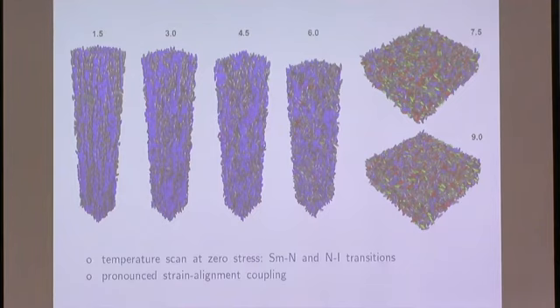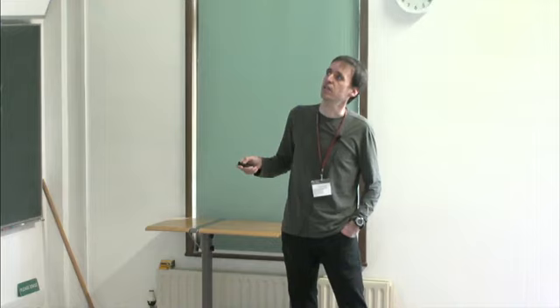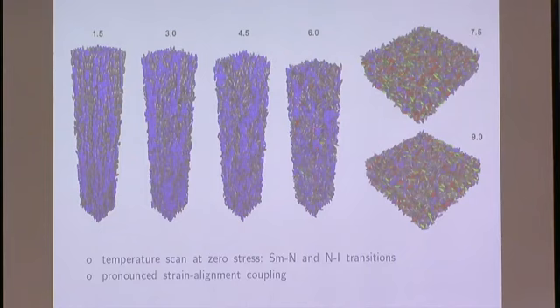Now, for example, we can reduce our temperature, and you can see that in this case, at T star equal 1.5, we have nice smectic layering. So we have a smectic here. Then on the other hand, if we increase temperature, the system will get a bit shorter, and the orientational order will be a bit reduced. And then between 6 and 7.5, we can see a clear transition from the aligned nematic phase to an isotropic phase, which is accompanied also by significant contraction along the previously imprinted z-axis. And so here you have all three colors represented more or less equally, so it's really isotropic, even more so for the even higher temperature.